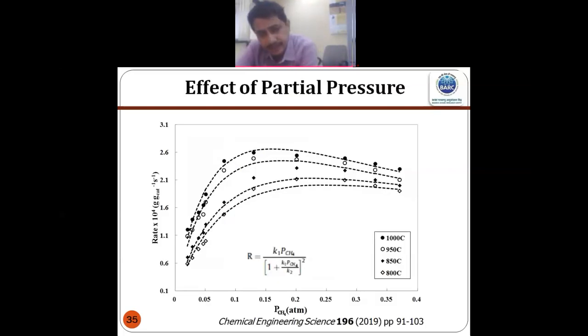Now if I see the effect of partial pressure here, this is slightly different from what we watched in multi-wall carbon nanotube. Here the deposition rate of carbon nanotube finally comes down when there is high partial pressure of this hydrocarbon. So that is why we should always synthesize the single wall carbon nanotube at a low partial pressure of hydrocarbon. We cannot match the production rate of single wall carbon nanotube with that of the multi-wall carbon nanotube.